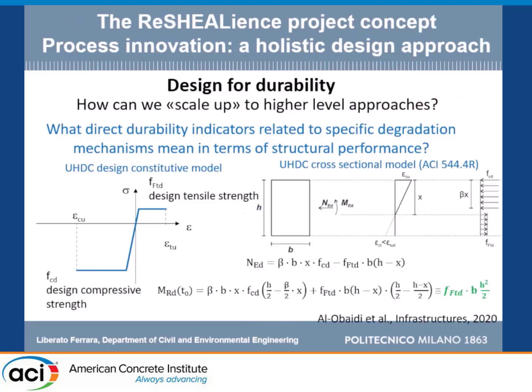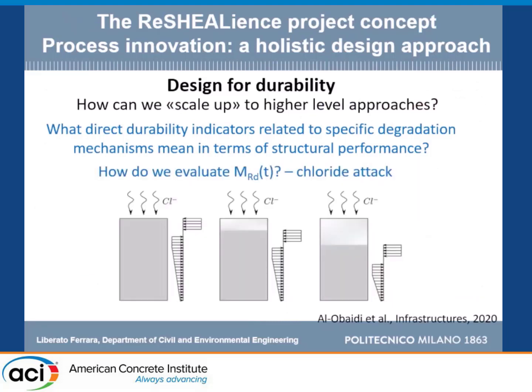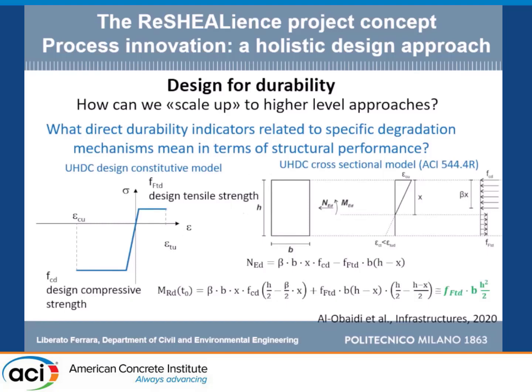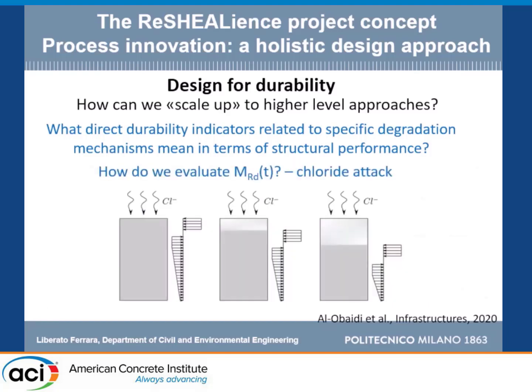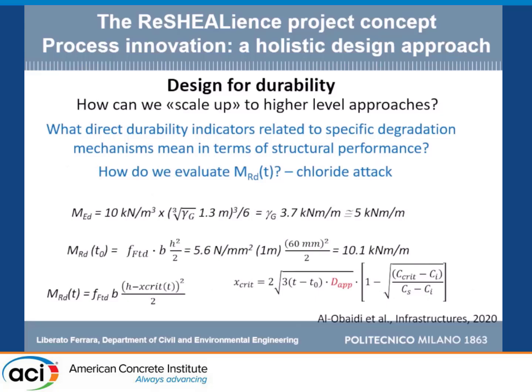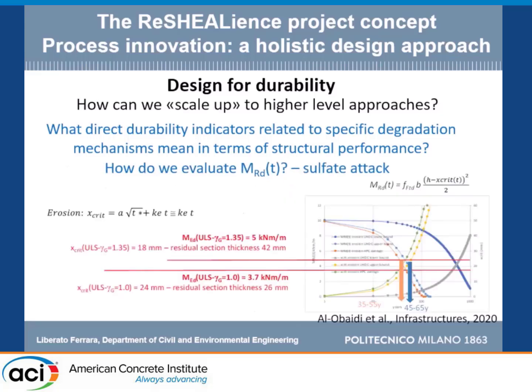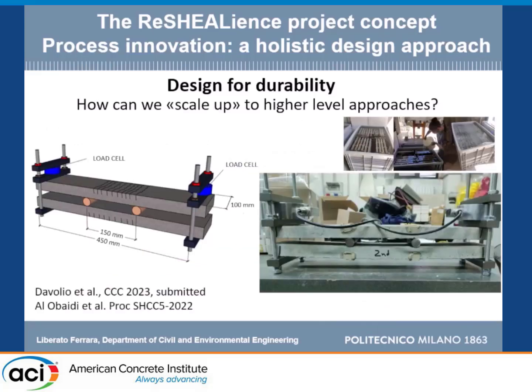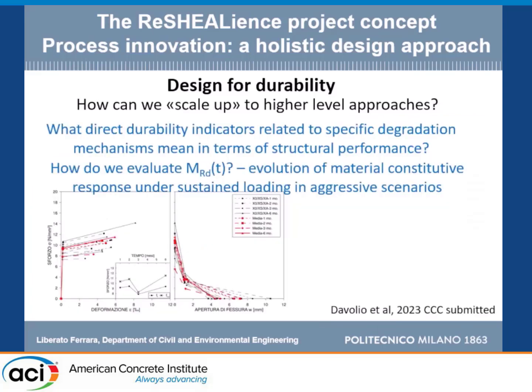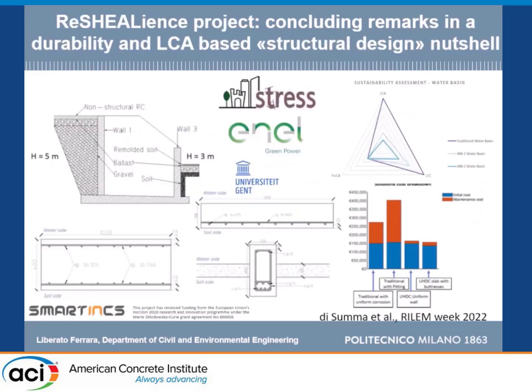So we embedded into structural design equations the degradation mechanism for chlorides or sulfates, ending up to predict the evolution of any indicator of mechanical performance, could be the maximum bending moment, so on, over time. So we demonstrated the increase of service life in going from ordinary concrete to ultra-high performance concrete. We validated it through laboratory results, and these are the results of the LCA, and these are the results of the LCC.